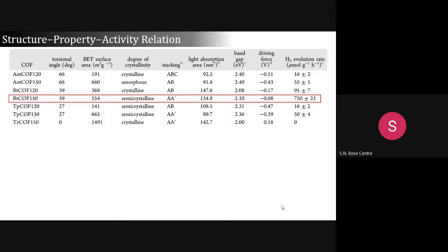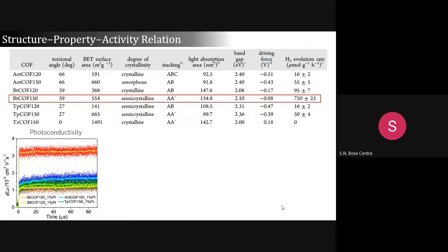Here you can see the band gap. The BT curve has a band gap of 2.1, whereas the TP curve has a band gap of 2.36. That means 2.1 will absorb more solar energy than the TP curve. But will this affect the hydrogen evolution to that extent? Because BT curve 120 also has a similar band gap. That is also crystalline, but the packing is different, like AB packing. Its hydrogen evolution rate is 750, while others are quite low compared to this one. So we need to look at some other parameters.